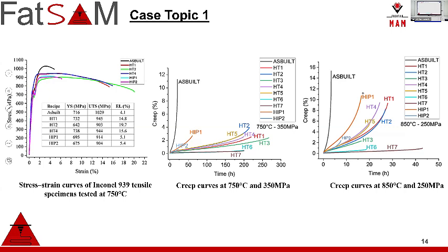The biggest advantage of vacuum heat treatment is that you can continuously heat treat after solution heat treatment, which can give you solution strengthening in the matrix, which is gamma, and continue directly to the aging steps. You can do ultra-fast quenching, then go to high subsolvus temperatures to obtain the desired precipitates, which is gamma prime in this case. So when we look at the creep properties, we have certain heat treatments and certain results, depending on the perspective of what you are looking for.